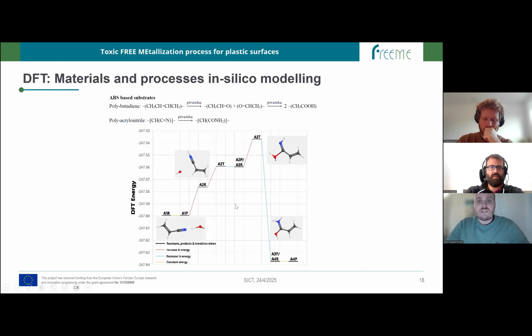amide group. Okay, so basically what we have found is that it's an exothermic process. So it's something that is possible to happen with maybe a little bit of energy, because we found that we have a transition, a rate determining step here that would correspond to the formation of this amide group. Okay, here the graphic is set in Hartrees. So that means that the barrier, the activation energy, sorry, for this process would correspond to approximately 0.8 electron volts. So that means that it can happen, but maybe we will require some kind of temperature in order to make